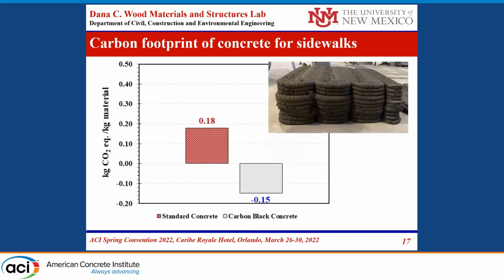This is the calculation we have for the carbon footprint. This is a standard calculation for carbon footprint, assuming that you have 1 ton of CO2 for 1 ton of cement when you calculate the mix. But here, what we are showing is a negative carbon footprint, because with the large replacement of the aggregate with the carbon black, this carbon black coming from sequestered CO2, we can consider it as negative. That's why we are showing it as a negative carbon footprint.